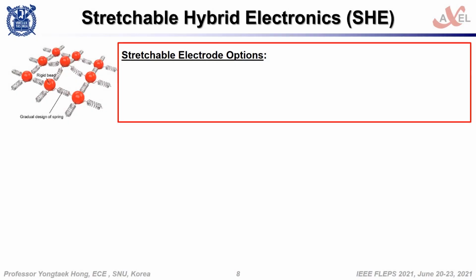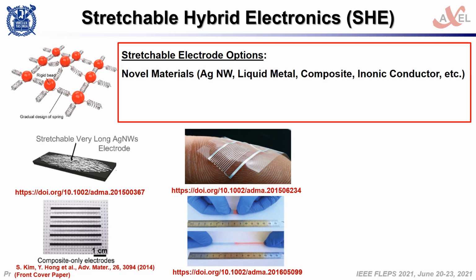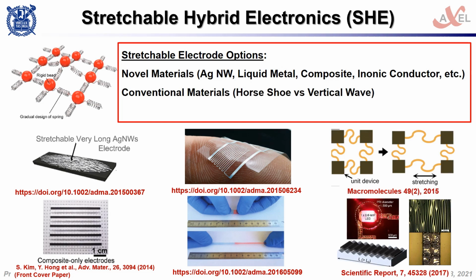Once we have stretchable platforms, we need to implement a spring-like stretchable interconnect between strain-engineered rigid areas. We need to consider fine patterning and high conductivity of the interconnect electrodes for highly integrated system. Novel materials show highly stretchable functions, but typically have difficulties in fine feature patterning and low conductivity. Structure-engineered conventional metals show high conductivity but limited feature in fine patterning and stretchability. Depending on requirements of various electronic systems, we need to carefully choose appropriate material and fabrication strategies.